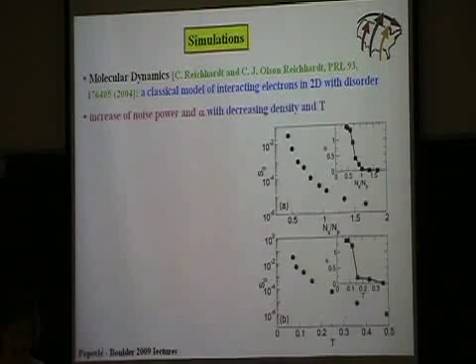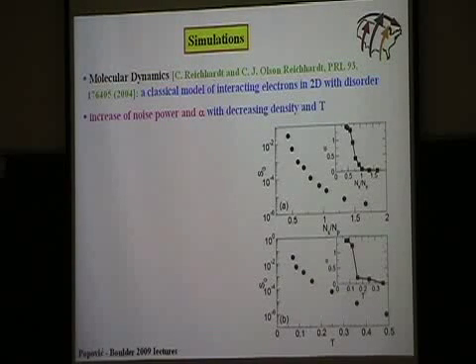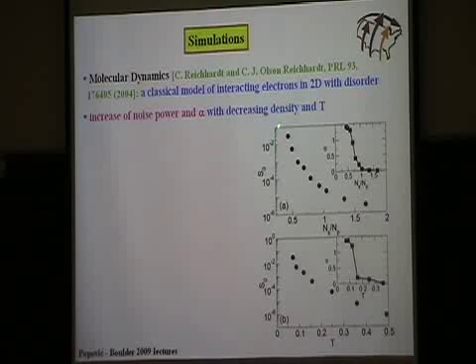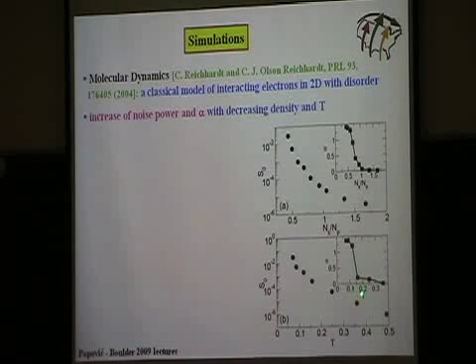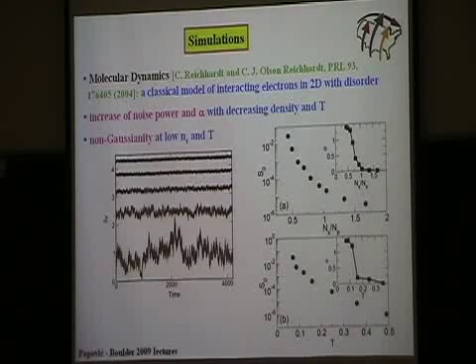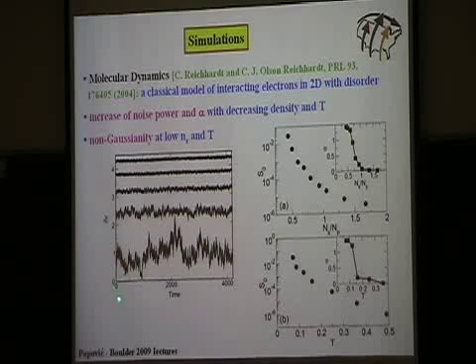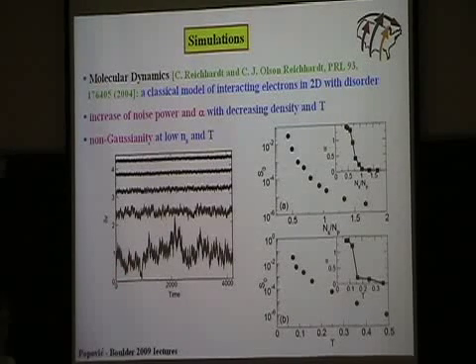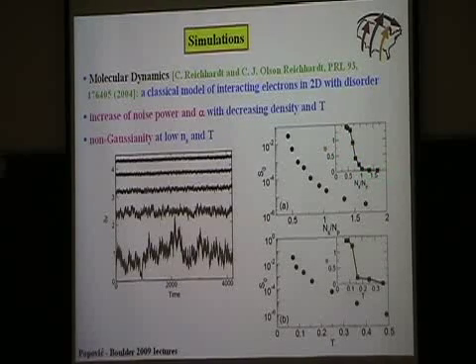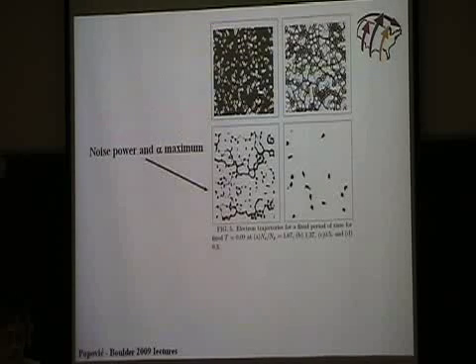Okay. So there have also been some simulations. Again, this was done by Cynthia and Charles Reichhardt. These are molecular dynamic simulations that were actually motivated by noise work. And they looked at the classical model of interacting electrons in 2D with disorder. So it's a classical model, but nevertheless they were able to reproduce some of the main features of the data. They found that as you reduce the density, the magnitude of the noise goes up, the exponent alpha goes up, and the metal-insulator transition, and also as a function of temperature. They were also able to find non-Gaussianity at low values of densities and temperatures. So this is very similar to experimental data. The details are not quite the same, like alpha is 0 here. But anyway, it's similar to the experiments.